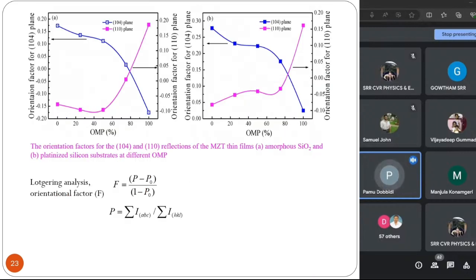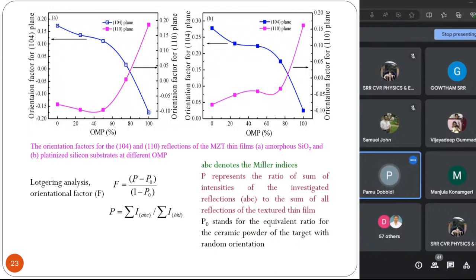Yeah, so here what is happening is that the beauty of thin film is that you can orient the direction of a thin film, like you have different lattice planes, right? 111, or 100, or 101, different planes. Because in the previous slide we have seen certain peaks are increasing. That means orientation is increasing. In some cases, it is decreasing with respect to the oxygen percentage. That's where OMP is the oxygen mixing percentage. Next slide, please.